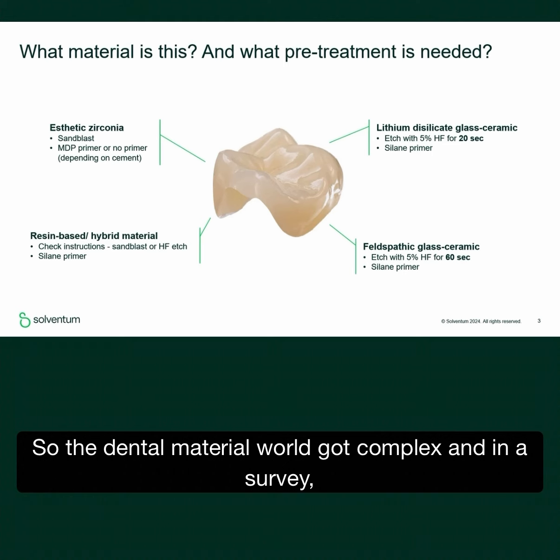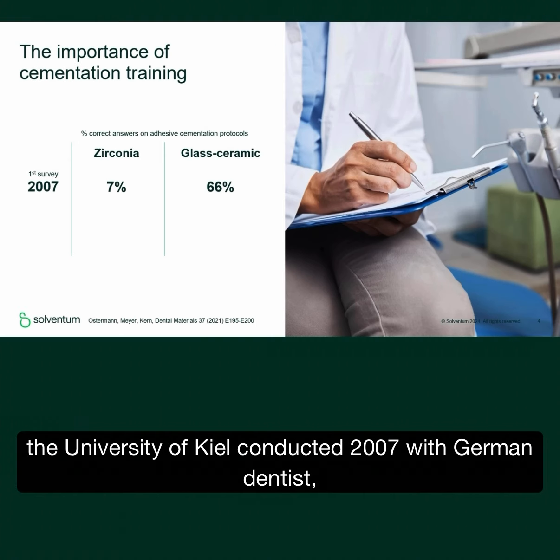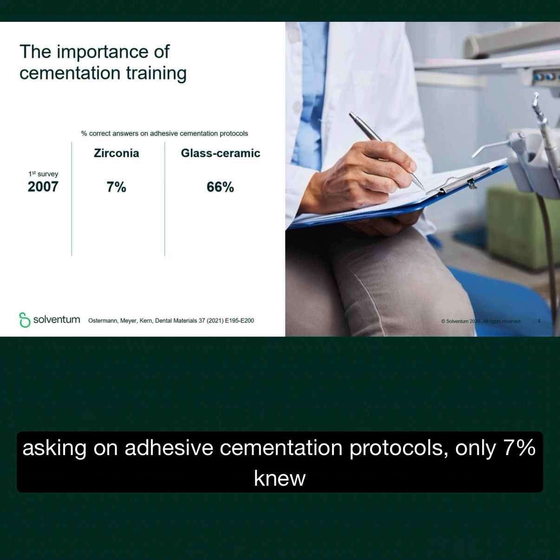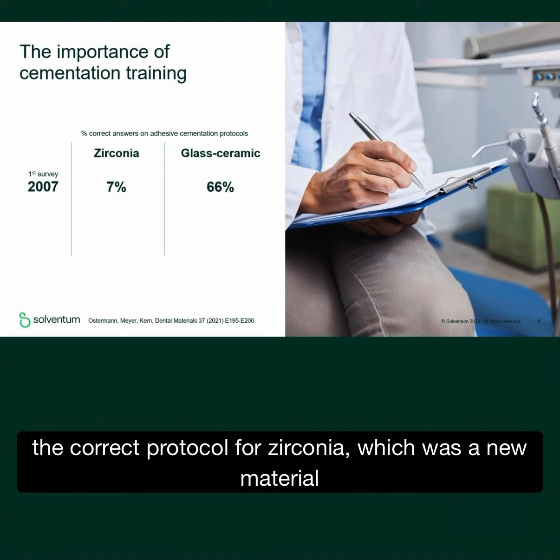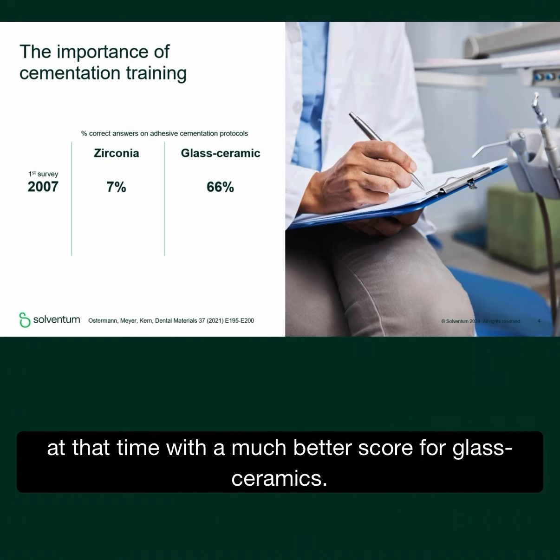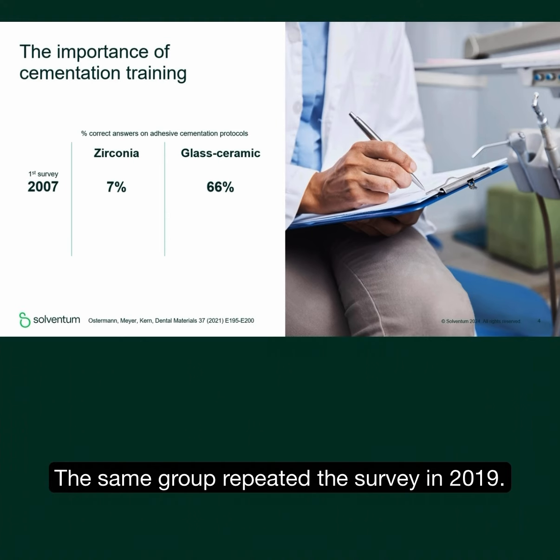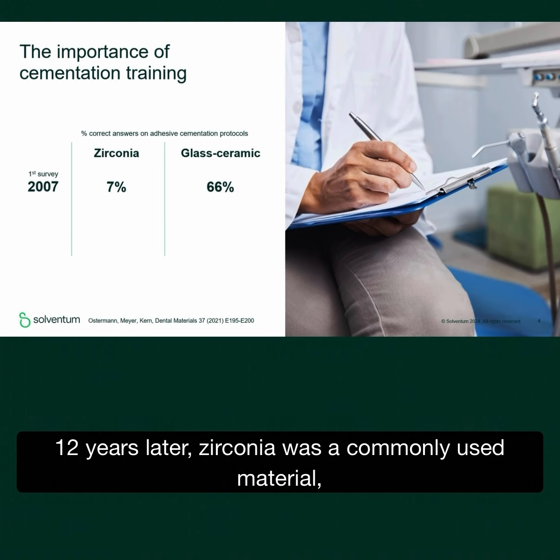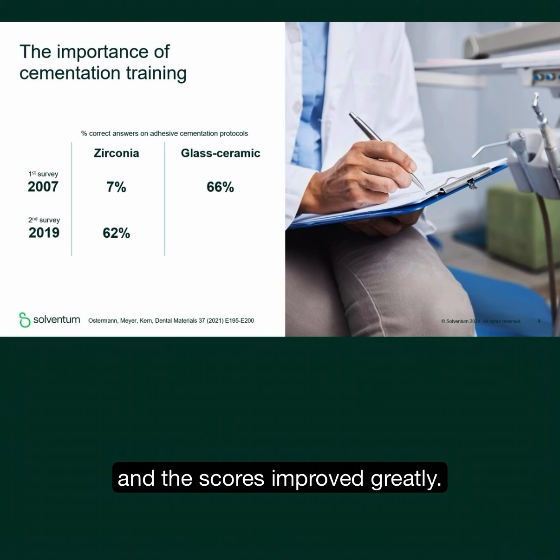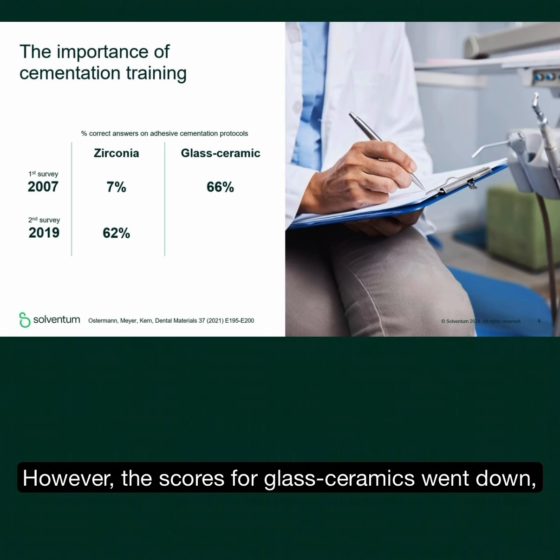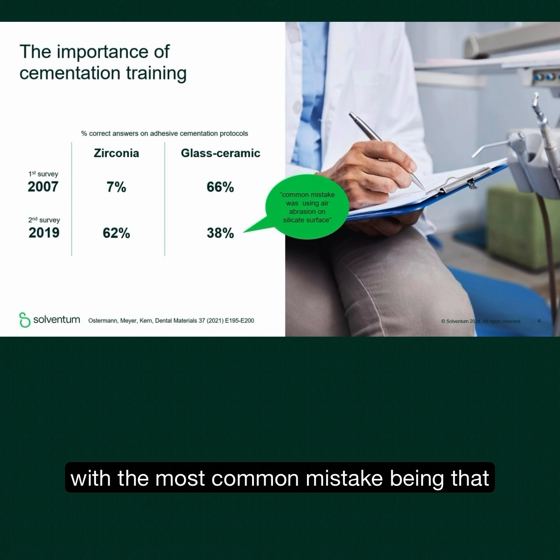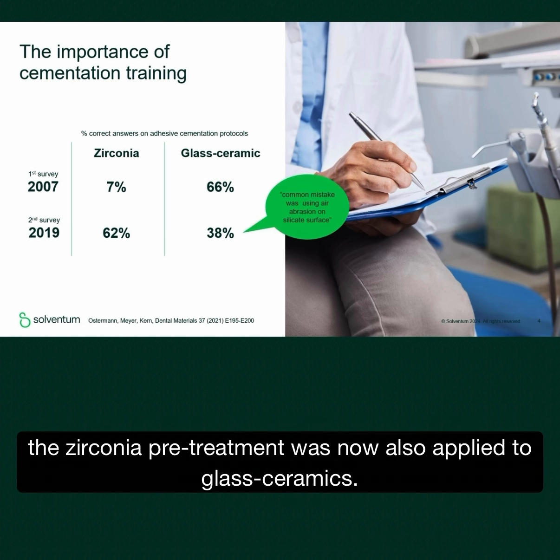So the dental material world got complex, and in a survey the University of Kiel conducted in 2007 with German dentists asking about adhesive cementation protocols, only 7% knew the correct protocol for zirconia, which was a new material at that time, with a much better score for glass ceramics. The same group repeated the survey in 2019. 12 years later, zirconia was a commonly used material and the scores improved greatly. However, the scores for glass ceramics went down, with the most common mistake being that the zirconia pretreatment was now also applied to glass ceramics.